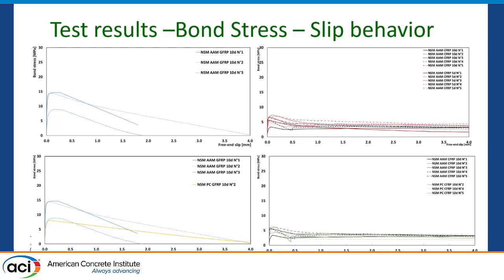Here we can see the bond stress versus slip behavior, this time only for the GFRP with 10D and GFRP with 2C for 10D. We see that the behavior is similar to pull-out tests, and we don't have the 5D bond stress curve because our cavity was destroyed. And for carbon fiber, we see the increase in the bond stress for the small levels of slip, and then reaching the maximum and decreasing to a certain point, and then continuing straight for both alkali-activated materials and for Portland cement materials.